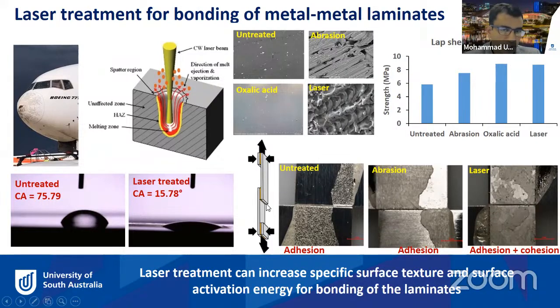And we have done some lap shear testing as well, to investigate the performance of the bonding, and we found that the laser treated laminate actually gives pretty much equivalent bonding strength to the commonly industry practiced treatment, which is the acid treatment. So that means laser treatment is more environment friendly as opposed to the acid based, which is toxic. So that was the main aim, to really develop a sustainable, environment friendly surface modification technique to improve the bonding strength.